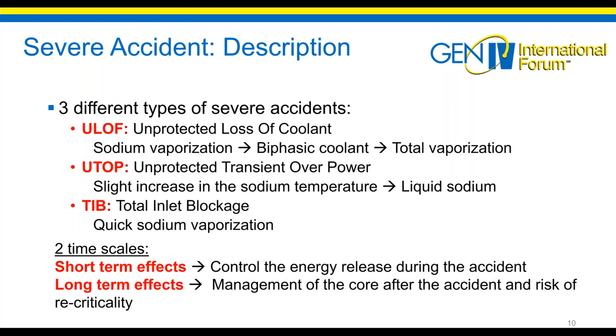Moreover, when you describe a severe accident, you have to take into account two timescales. The first one is the short-term effects, where you have to control the mechanical energy release during the accident in order to avoid the break of the confinement and the release of radioactive materials into the environment. And then you have the long-term effects that deal with the management of the core after the accident. In fact, you have to be sure that a fission reaction will not start again after the accident.